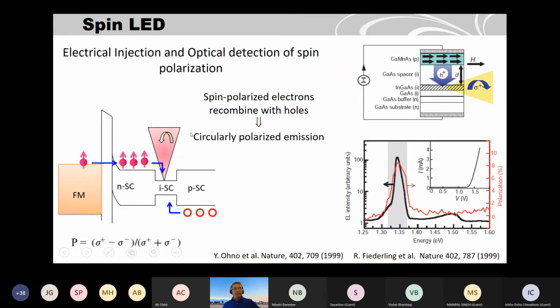They recombine and create light. But if you use spin, you want to make a spin LED. So what we can do is inject spin polarized electrons from the ferromagnet. And this semiconductor should be of such thickness that spin can survive and come to this quantum well. And they recombine here, and the light coming out from this LED will be circularly polarized emission. Okay, and people have detected this with electroluminescence intensity. This is the polarization of the light coming out, and this was done around 2000 in these two papers.